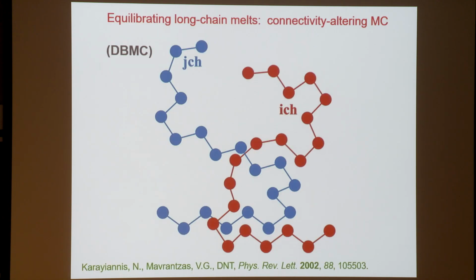So let's start with the problem of equilibrating polymer melts and getting properties of these melts through simulation. As we mentioned, molecular dynamics falls short of the longest relaxation times of these melts if the molecular weight is very large. So since early times, our group has focused on Monte Carlo simulations to accomplish this equilibration. And what has been particularly useful is these connectivity altering moves.